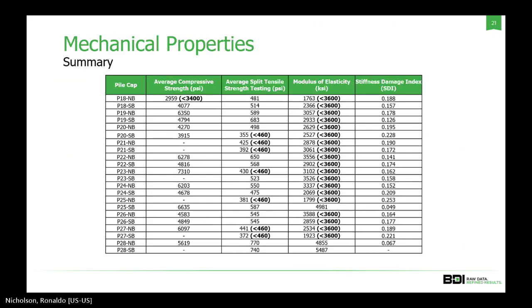Pretty straightforward. Average compressive strengths, the tensile, modulus of elasticity, and stiffness damage testing were reported, where the values in parentheses in bold were some of the limits based on the design values for the original designs. So as you can see, strength was pretty okay. A handful of lower split tensile locations, but in general, fairly low modulus of elasticity. So I'm sure that Nick could probably tell you that all of these were used to make sure that the design was appropriate for these mechanical properties of the concrete.